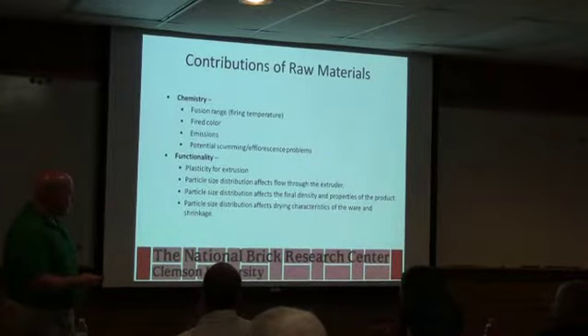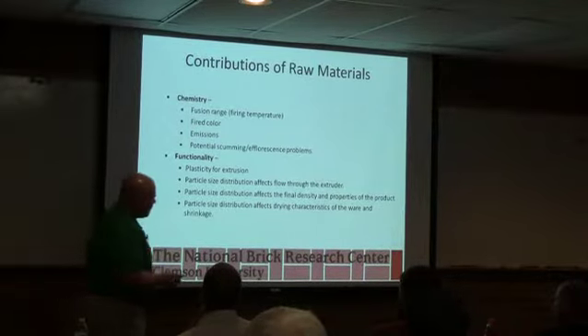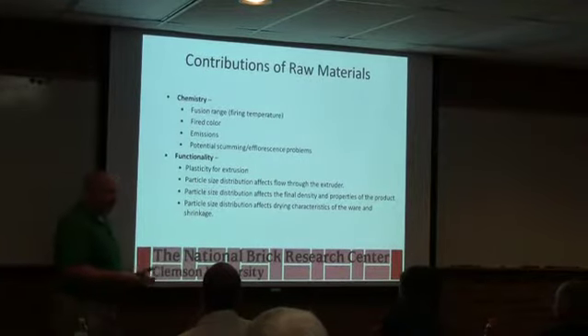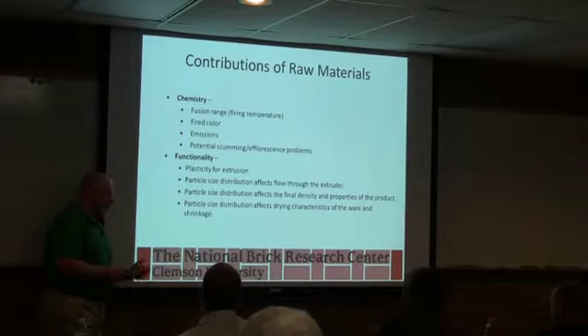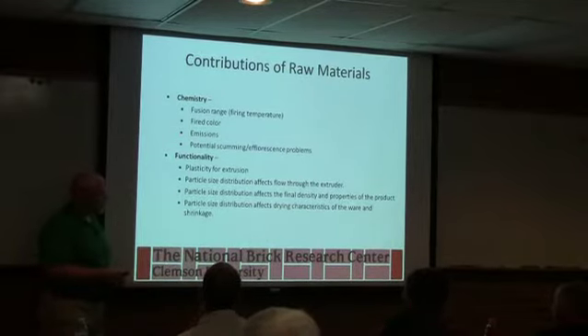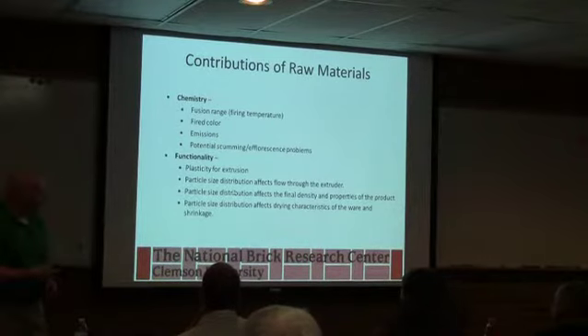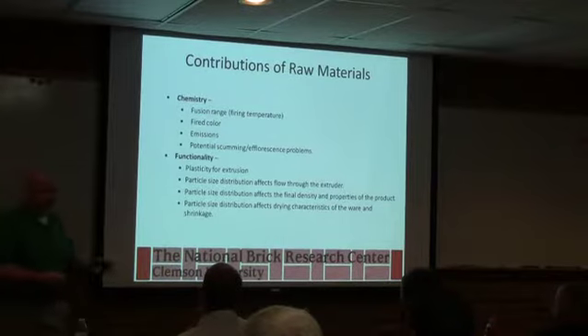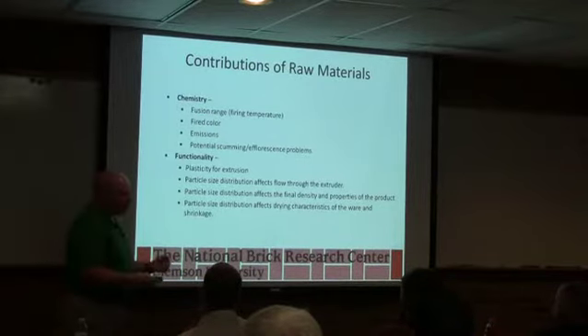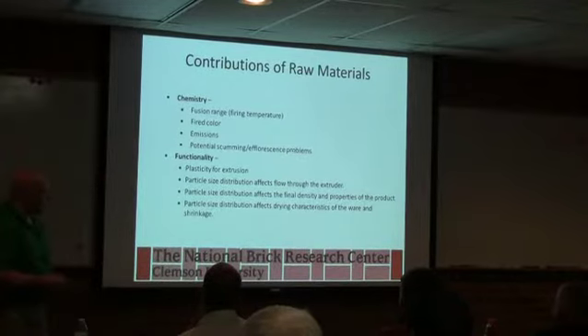The way the particles pack together. So the particle size distribution affects the density and the properties. So if I can get the materials to pack together better in extrusion, I may see less shrinkage, I may see a lower water absorption. And typically, one of the easy ways to do this with a lot of materials is to add a little bit of soda ash. But the problem is you get a tighter body, it's also harder to dry, okay, because there is not as much channel for the water to get out.